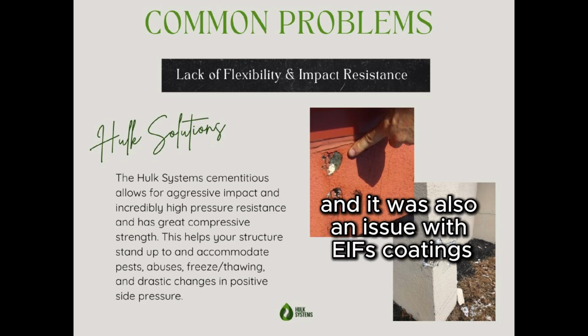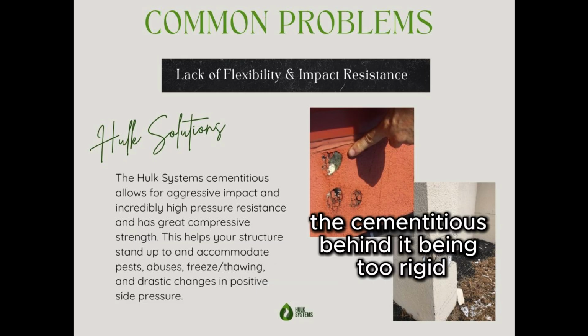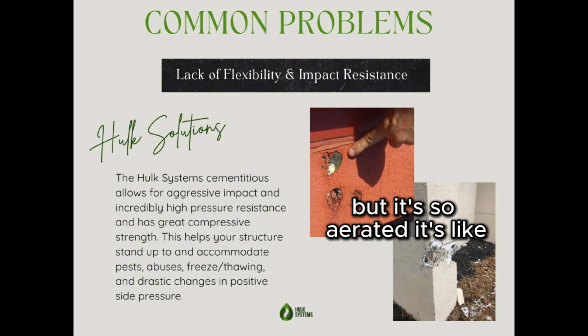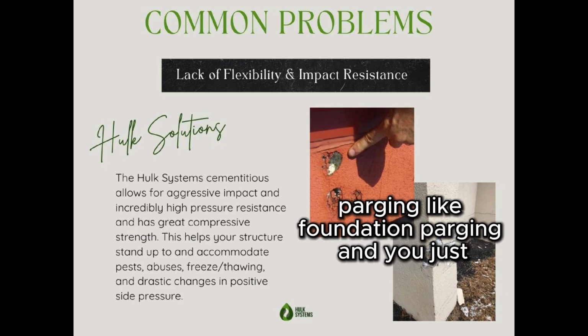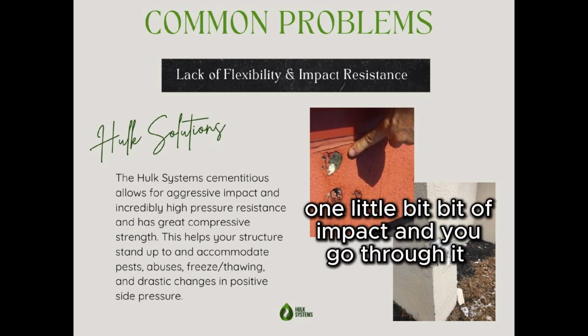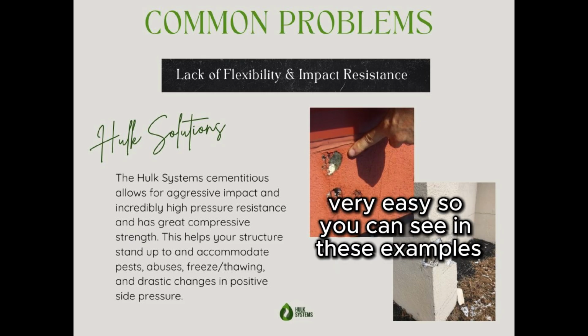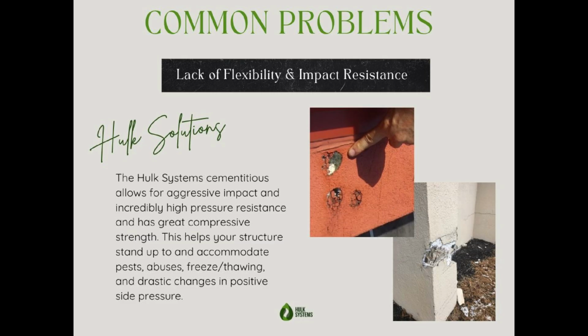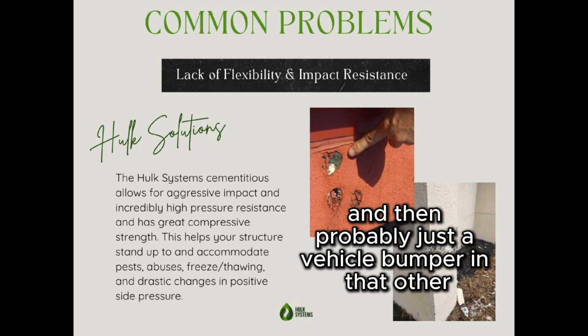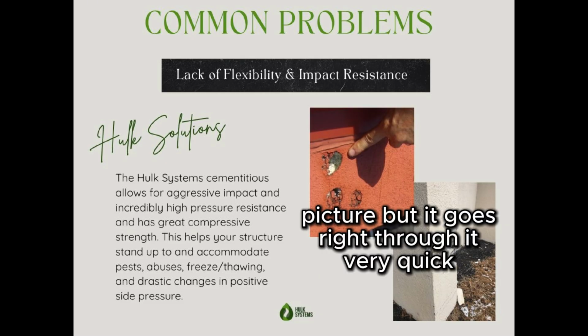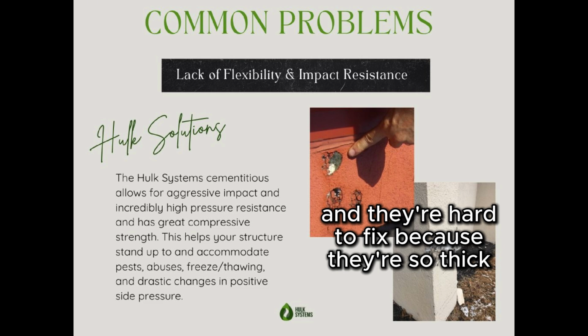And it was also an issue with EIFS coatings. So EIFS, the cementitious behind it being too rigid, really aerated. It can be this thick, but it's so aerated, it's like parging, like foundation parging, and just one little bit of impact and you go through it very easy. So you can see in these examples with impact resistance, that is EIFS on both those examples. And you've got hail damage, and then probably just a vehicle bumper in that other picture, but it goes right through it very quick. And they're hard to fix because they're so thick.